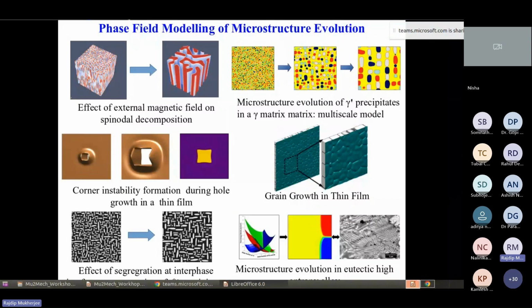Yes, yes. So in metallurgy, we do it in the opposite direction, meaning you have a liquid, and if we cool it below the eutectic temperature, it solidifies into a two-phase microstructure. Like you were saying, there are A and B components; if you heat it above the eutectic temperature, it will be liquid. But in our cases, we do the opposite, the solidification. But you can always do the melting also. That is also possible.